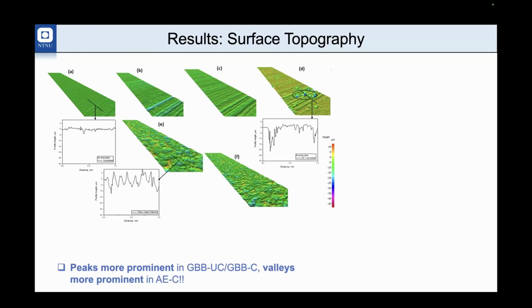In contrast, if you look at the 24-hour corroded specimen, you see there are deep valleys. That's because of the significant material loss by corrosion, formation of pits and intergranular cracks. You can see the 3D topography there. On the other hand, if you consider the glass bead blasted one, you see there is formation of bulged craters. So rather than valleys, there is some formation of peaks.